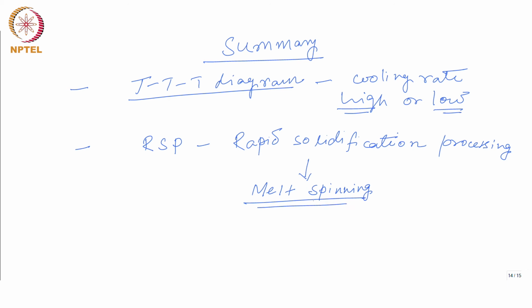In which the molten metal is allowed to drop on a rapidly rotating water cooled wheel made of copper, and as the molten metal falls on this rotating wheel, it provides a chilling effect, and due to that it immediately solidifies in an amorphous solid, which is thrown off from the wheel due to the centrifugal force in the form of a thin ribbon. Which is like 25 to 100 microns in thickness, and this can be easily broken down by mechanical attrition to generate angular powder.